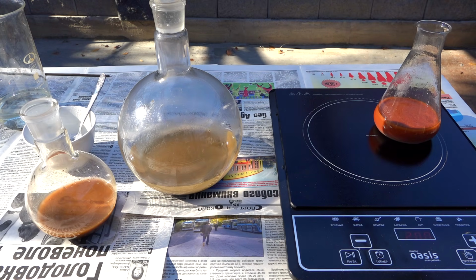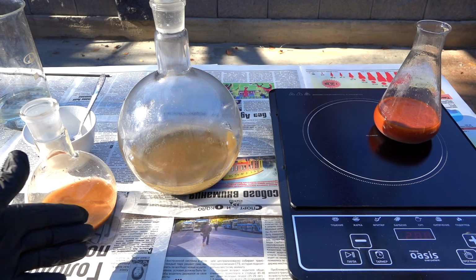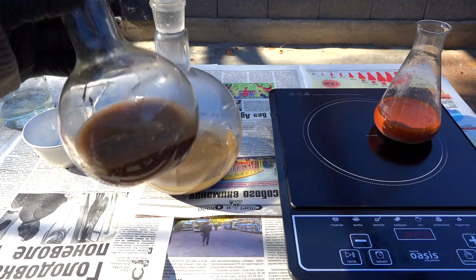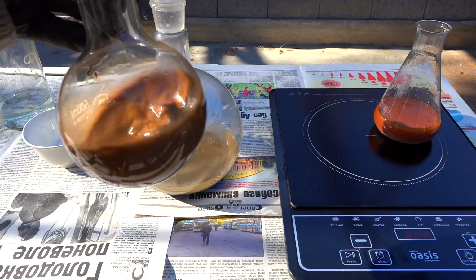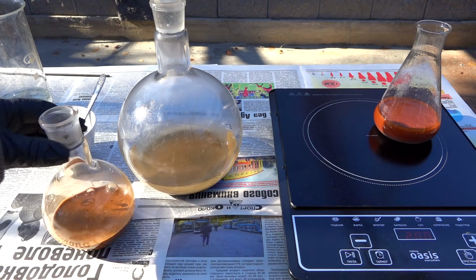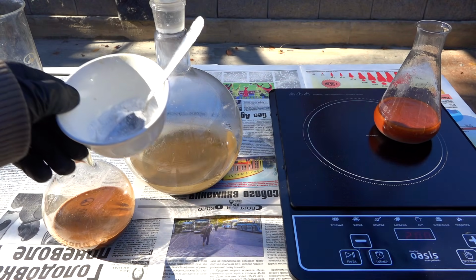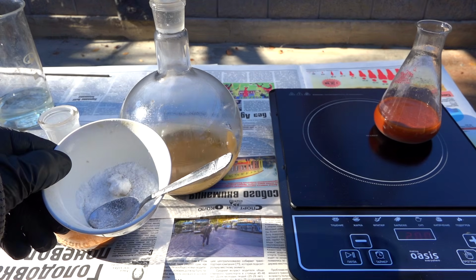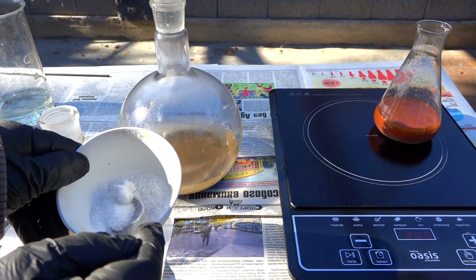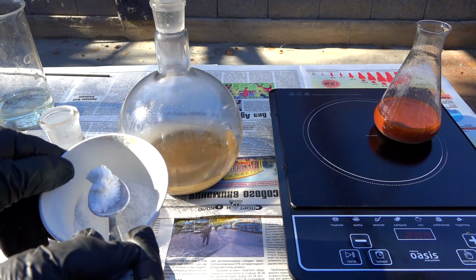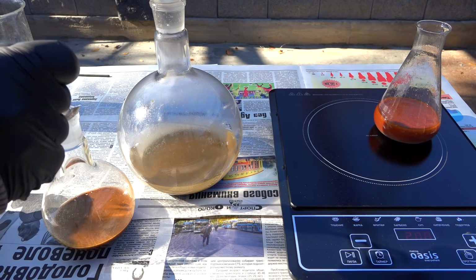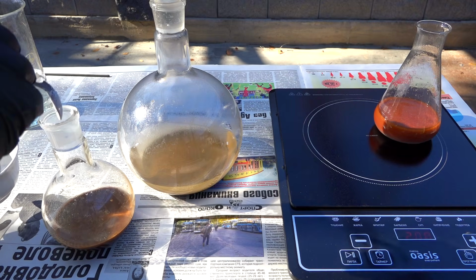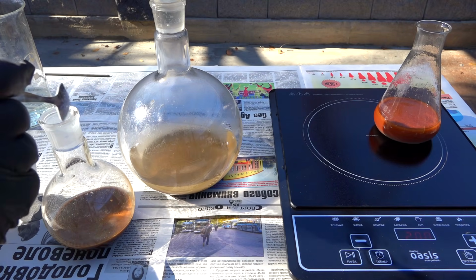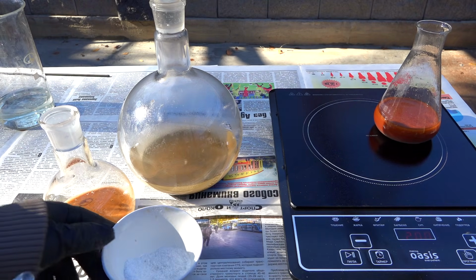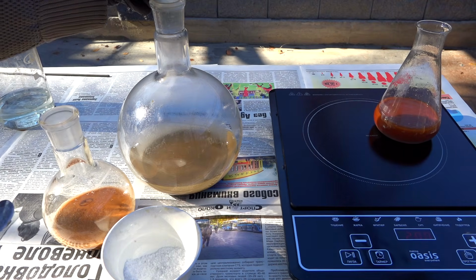The next day, I start chemistry. I'll use the simplest dissolution method: salt, sodium chloride, and nitric acid. This is the cheapest way to dissolve gold and concentrate in small volumes. Dissolving all the concentrate after centrifugation is no longer cost-effective and pointless. I also test other ores for precious metal content in small flasks, but that's not relevant to this topic.